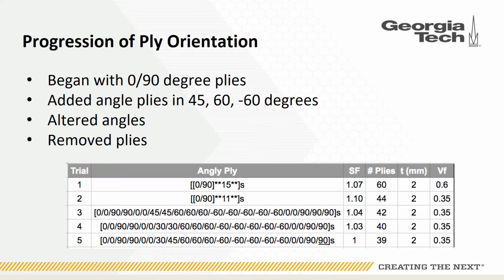After optimizing the fiber volume fraction, we began working on the progression of our ply orientation. First, we began with only 0 and 90 degree plies. However, even though we did not have shear forces, we found that it was beneficial to have 45, 60, and negative 60 degree plies included. We later started altering angles as we saw certain plies failing to help spread out the loading, and eventually we were able to remove multiple plies. This led us going from 60 plies in our first orientation to only 39 in the final.